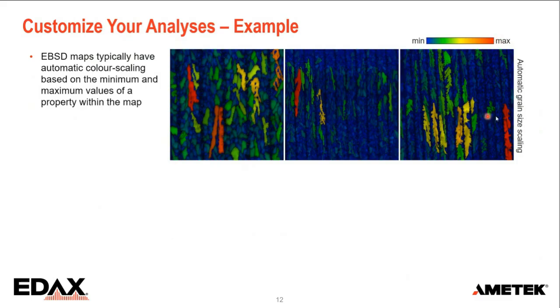And in this case, it almost appears that the image on the left gives you a larger average grain size. But of course, we have to be a bit honest here. I didn't put a scale bar on. So if I put a scale bar on, you can see that the maximum grain size here is only about 3 micron. And here it's over 10 micron.